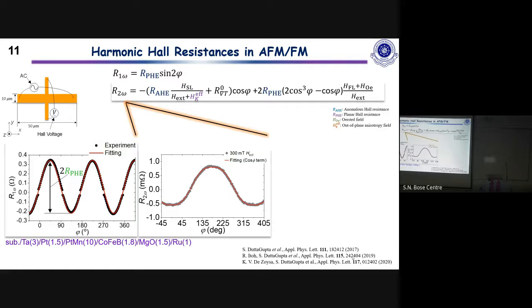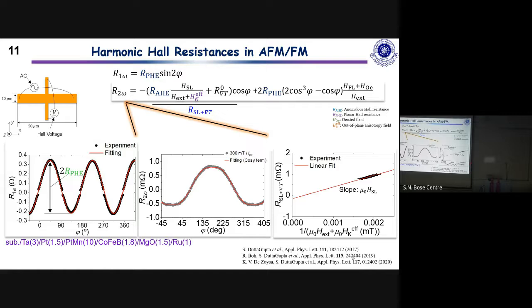And then we did this same experiment by varying the magnetic field. So this is for 300 millitesla, but we did it for various different applied magnetic fields. And then we can plot this curve. This is basically the coefficient of the first term as a function of this external field. And the slope of this graph gives you this effective field which is coming from the spin Hall effect. So we can also do the same thing for the field-like torque, and we quantify both of them.